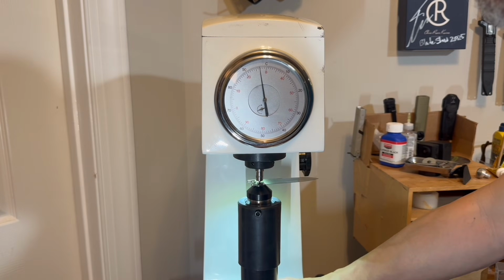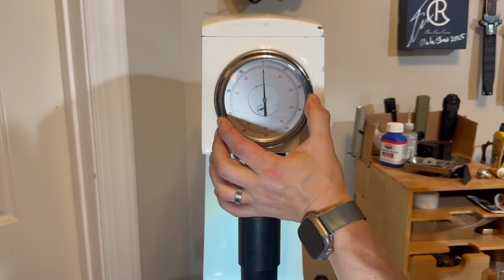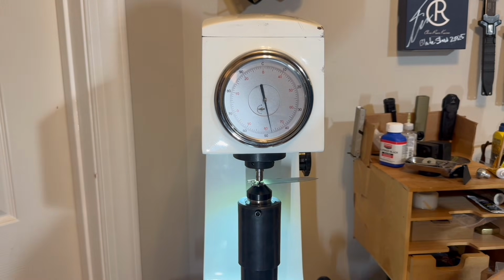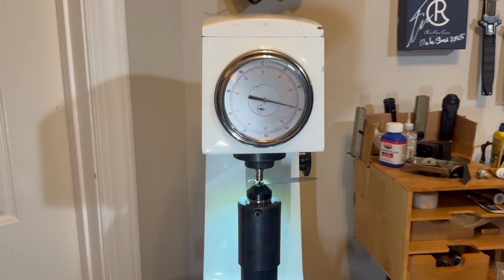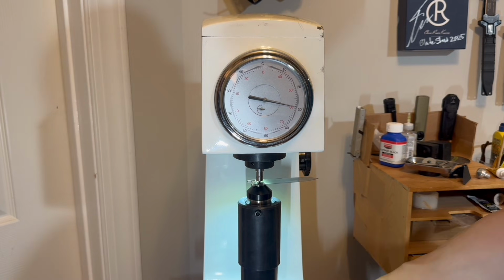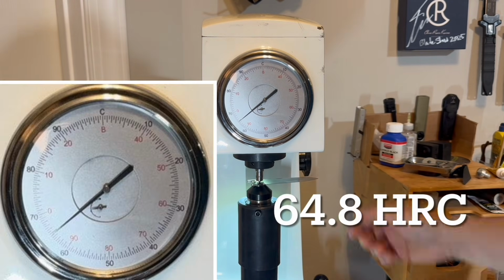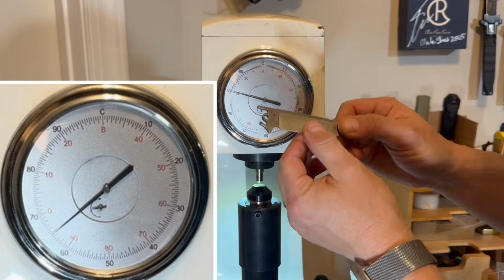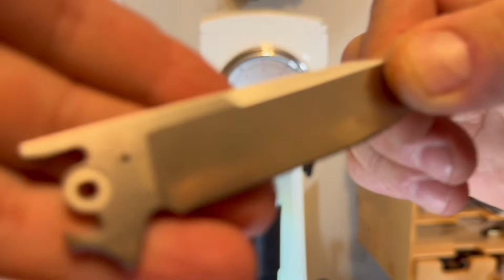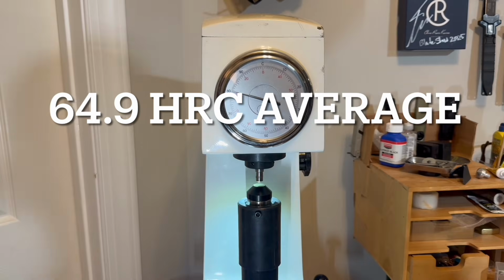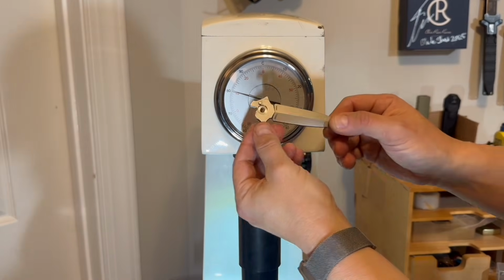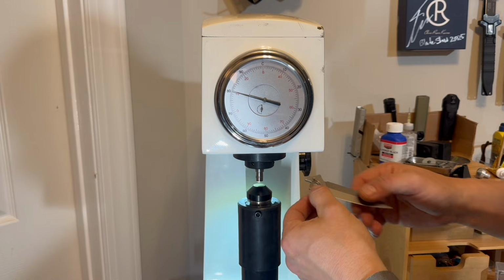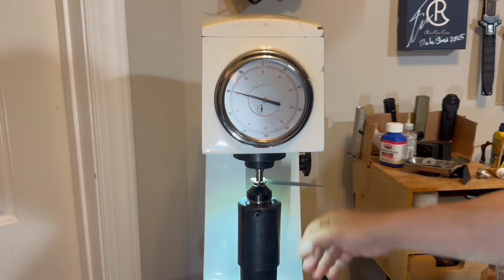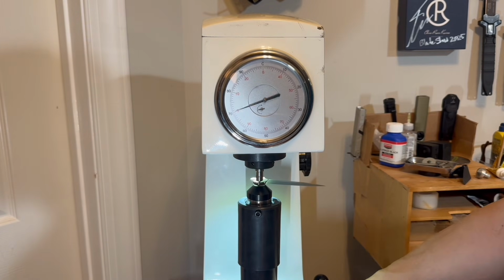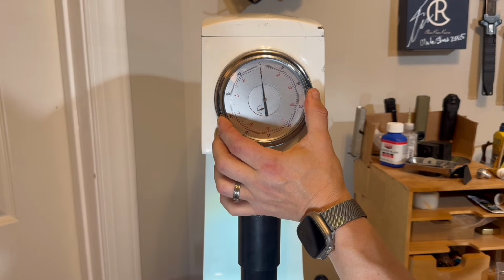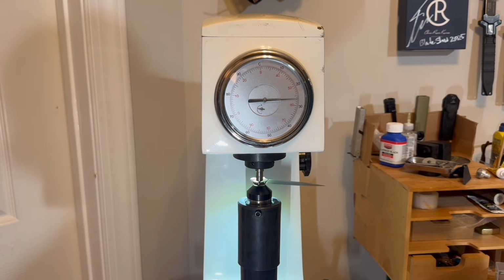Clearly, there's nothing wrong with my Rockwell tester, as you will see later as I test the other blades. It's just what this blade is heat treated to. Doing a third poke just in case, and then I'll average them out. 64.8 again, so the average for this blade is huge, 64.9 HRC, and that worries me quite a bit, and I'll talk about why I'm so worried a little later in the video.